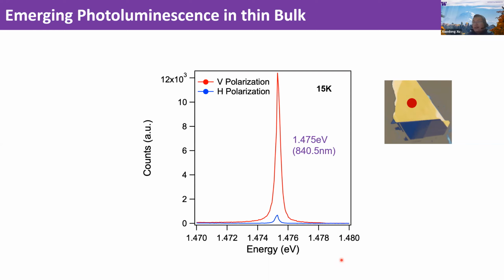Before, we tried quite a few different materials, and this is the one that actually shows really nice exciton luminescence. First of all, you see here a really pronounced luminescence at around 1.475 eV. This is basically a 40 nanometer sample, measured at a temperature of 15 kelvins. The first thing that really got my notice is the linewidth. The linewidth of this peak is really narrow, only 350 micro eV.